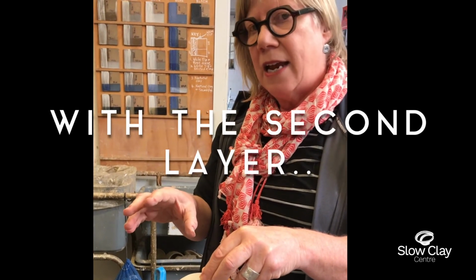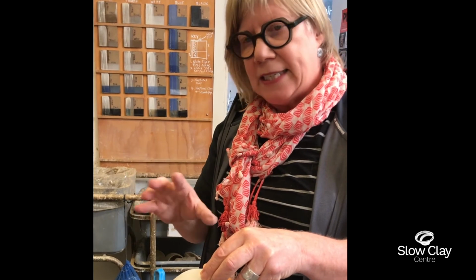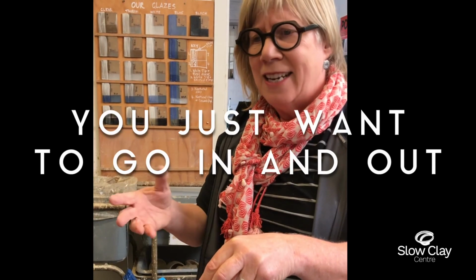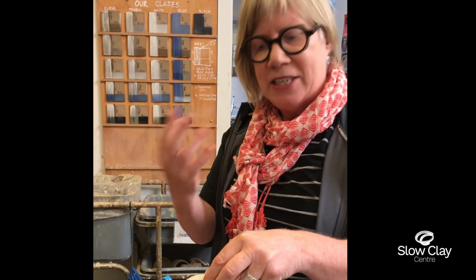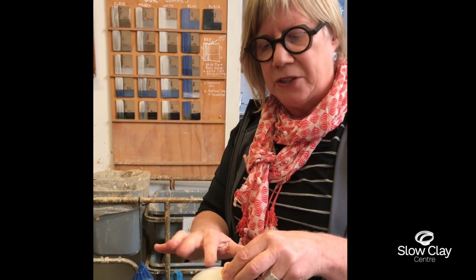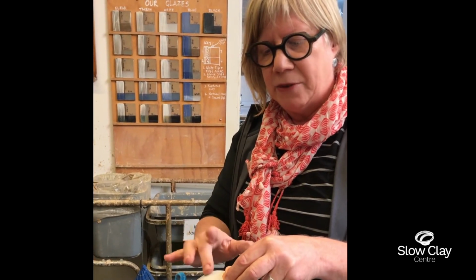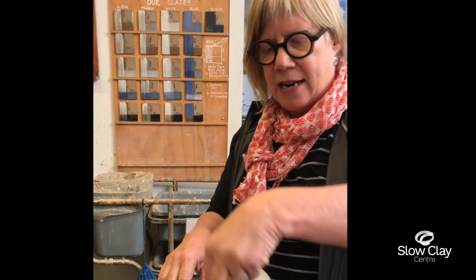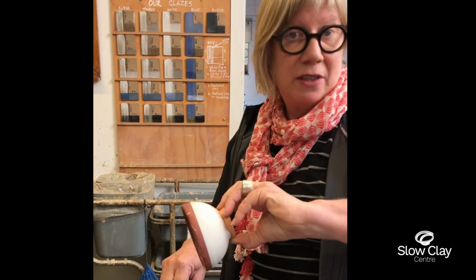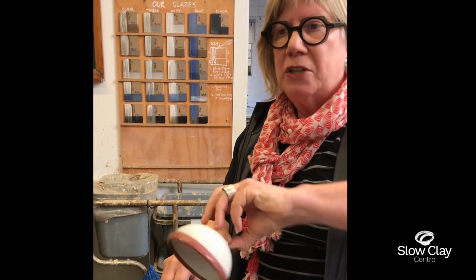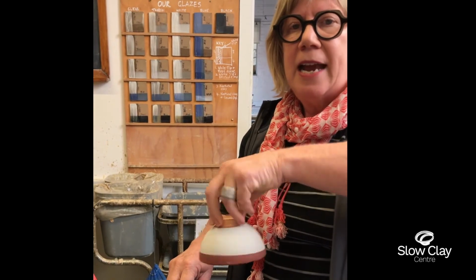I didn't even count, because with the second layer, it won't stick to the first layer if you're holding it under for any length of time. So you just want to go in and out, and the second layer will then have a chance to stick to the first one, which is already touch dry but still has a little bit of moisture in there. And then the second layer will probably take longer to dry because of all that moisture that's in the clay.